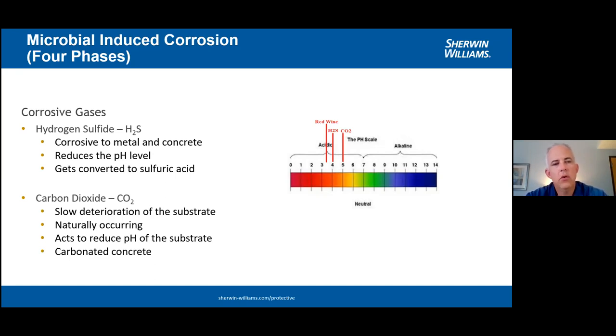So we have basically two corrosive gases in our sewage collection system and also in our wastewater treatment system. First one is hydrogen sulfide. Hydrogen sulfide gas is extremely corrosive to metal and to concrete. And it attacks concrete by basically reducing the pH level. Happy concrete, concrete that's not being destroyed, if you will, happy good concrete has a pH of over 9, 10, in that range. This hydrogen sulfide gas works to reduce that pH level, and it also gets converted to a sulfuric acid as part of the system. We'll talk about that a little bit more here in just a second.